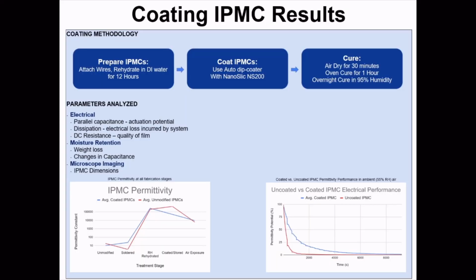So once we had this connection, we then had to go and actually coat these. The way you would do this is attach the wires, rehydrate them in water, and then use an auto dip coating machine to get a consistent coating every time and dip it in this coating that we established, NanoSlic NS200. Then we cured it according to the actual directions. So you can see that there.